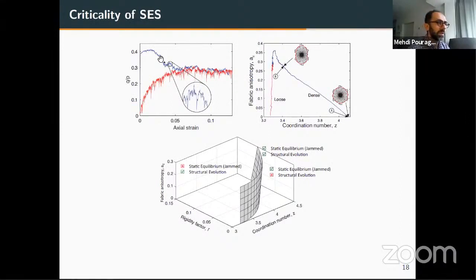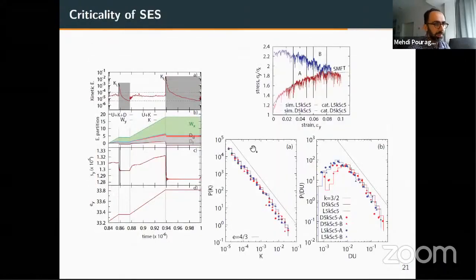So this is a little bit different. Basically, we are saying the state of these two materials should be very similar. They're both at a limit, and that's what we are seeing here. The blue lines refer to the statistics of the drop in the elastic energy stored in the material and the kinetic energy. We have the blue lines for the loose cases and the red lines for dense cases, and we see that they follow the same curve. So basically, the state of the material is indistinguishable for the two cases, which is consistent with the prediction of the SES theory that I talked about.